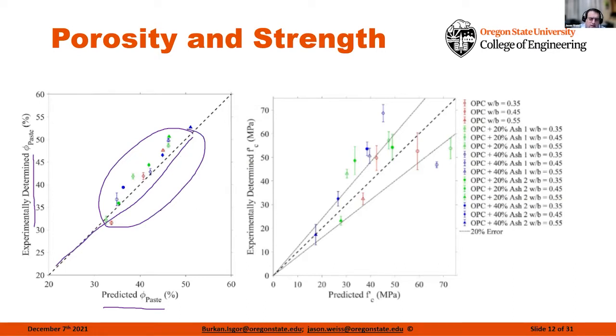We can do the exact same thing now, scaling this up and really going to compressive strength. And what we start to notice is for all of these systems, we're able to predict the compressive strength reasonably well. And the exciting part about this is all of these ashes that are shown here are ashes that are not standard fly ash. They're ashes that are off-spec fly ashes. They don't meet the current specifications. They would currently be landfilled. But what we've been able to show for the Electric Power Research Institute is that most of these materials, in fact, all of the materials that we tested, could be used to make very good concretes if we simply do the mixture proportioning correctly in these systems.